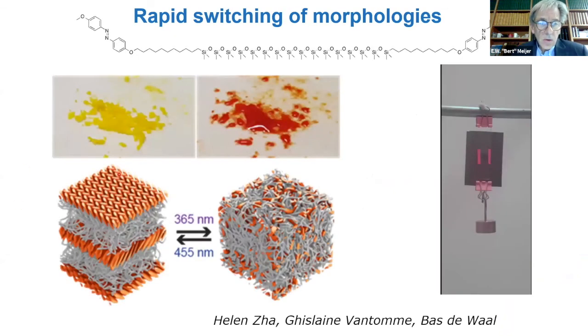And as you see over here, this is the crystal, yellow, this is a trans-azobenzene. But if you shine light on this of 365, it goes to cis, the order is gone. If you now take 455, it goes back to the trans, and it goes so fast that you can't actually measure how fast it goes. Normally it takes time, but it not only goes back to the trans, it also goes back to crystallization. I showed you before that in these phase separated states, the crystallization is so fast that you actually can't follow how fast it goes.